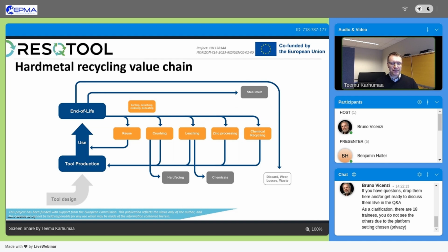Then some part goes to crushing, and the majority of this crushed hard metal goes to hard facing applications. So the nice wear protection and wear properties of hard metal are utilized, so that some steel parts are coated with crushed hard metal to prevent wear. Then there are companies doing leaching, which means the cobalt binder is removed from the hard metal scrap by acids, and the remaining tungsten carbide is returned to tool production, and the leached cobalt can be used as a raw material for different kinds of cobalt chemicals production. Then the two main processes for hard metal scrap are zinc processing and chemical recycling, and about them I will give a couple more details later.